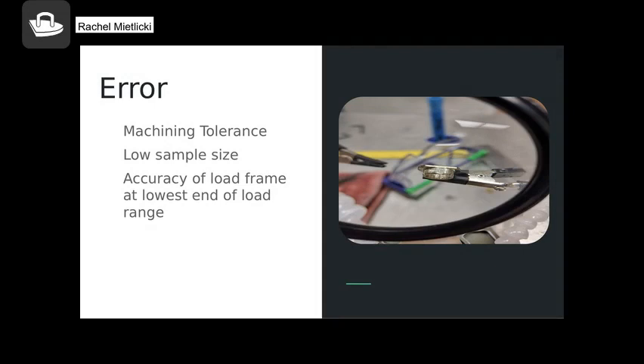In terms of error within our project, there's definitely a couple areas that can be touched upon, as each one of these could have impacted our results. First and foremost, when machining the manganese bronze bushings, the lathe that we were using had a tolerance of about 20 thousandths plus or minus in the cross carriage, so every diameter was harder to reach an ideal dimension based on the drawing. One of the bushings that we made came out perfectly to dimension, and the other was about two to three thou under for each diameter measurement. It's unclear whether the difference in sizing of diameter was the reason for failure, premature failure, of the manganese bronze bushing, as the undersized one was one that began to rotate within the frame, but definitely something important to note.